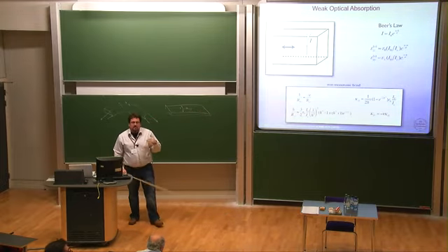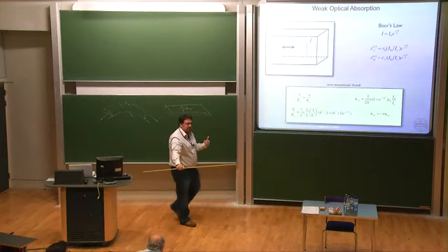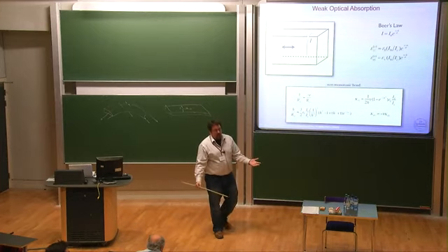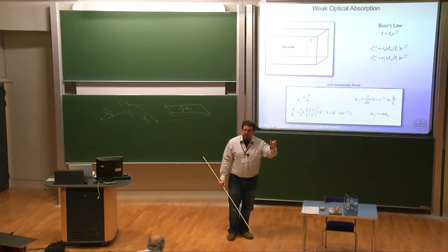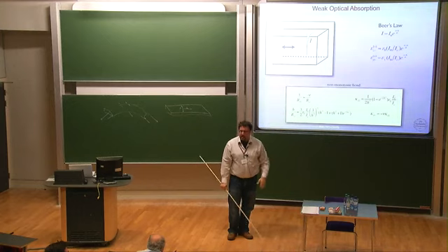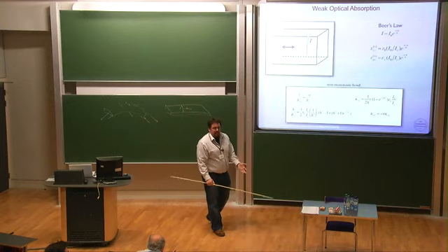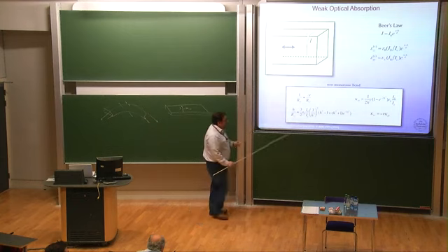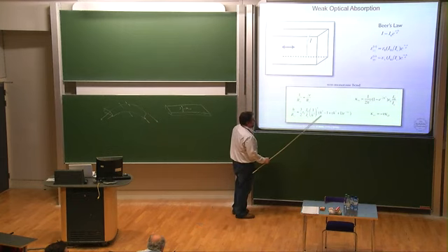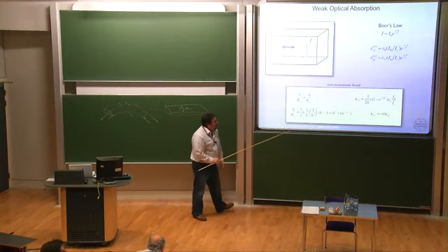So if you have a material that is very, very thick relative to the penetration depth, what's going to happen is you'll get some deformation gradients in a thin little surface layer, but then most of the material is just going to be this monolithic block. So it's just going to sit there. There's going to be very, very little bending, and that comes out from the form of the equation.